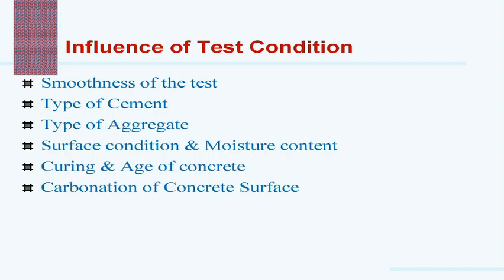Last one, that is the influence of carbonation of concrete surface. The influence of carbonation of concrete surface on the rebound number is very significant. Carbonated concrete gives an overestimate of strength, which in extreme cases can be up to 50%. It is possible to establish a correction factor by removing the carbonated layer and testing the concrete with the rebound hammer on the uncarbonated surface.